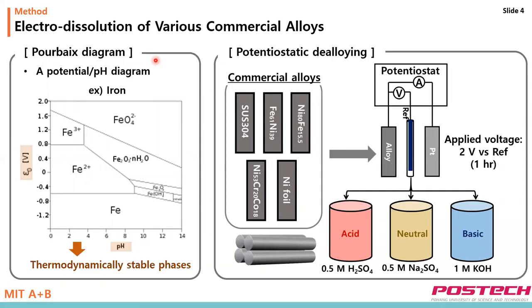Therefore, this study examined various commercial alloy materials as an electrocatalyst by using the electrodissolution method. Based on the Pourbaix diagram, there are thermodynamically stable phases of an aqueous electrochemical system. Therefore, in this system, different types of commercial alloy were activated by potentiostatic de-alloying method under certain pH conditions. This approach allows some elements to be selectively separated and removed from the alloy, so a surface with a new composition can be formed through the electrodissolution method.